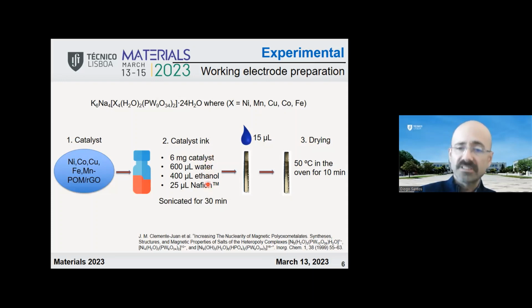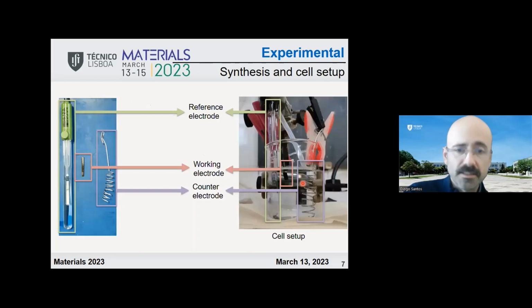Then we put water and ethanol and Nafion that works as the binder to bind the catalyst to our electrode surface. So then we just simply put a small amount of this material on the electrode, like 15 microliters of this ink. We let it dry for 10 minutes in the oven at 50 degrees Celsius, and the electrode is ready for the electrochemical testing.